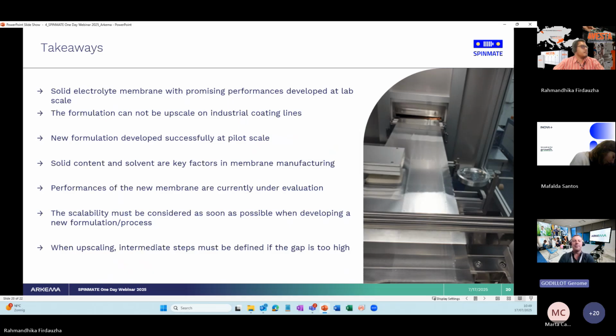So now some takeaways. I showed you that during the SPINMATE project, and with the help of CIC energiGUNE, we developed a solid electrolyte membrane with promising performances. It was at lab scale. Despite all our efforts, we were not able to upscale it on our coating line, and it looks like it will be very difficult to do on general industrial coating lines. That's why we worked again on the formulation at lab scale to develop a new formulation and a new process, and we successfully upscaled it at pilot scale. As I said, Abby will be in charge of the last upscaling from pilot scale to industrial scale.